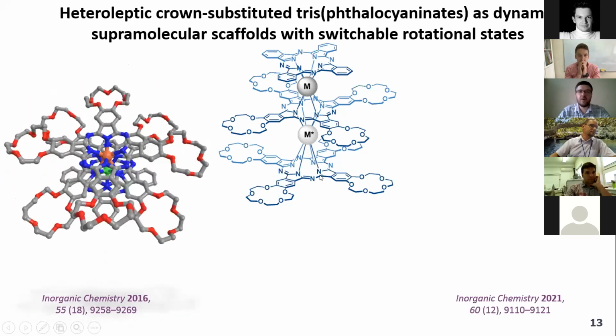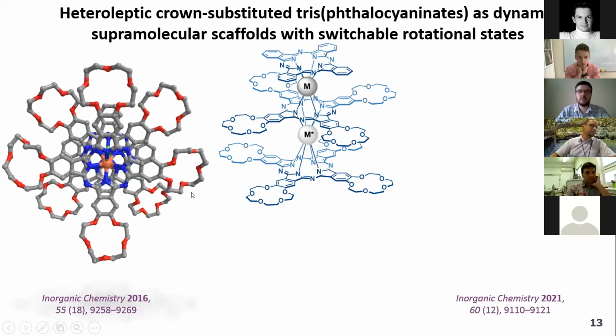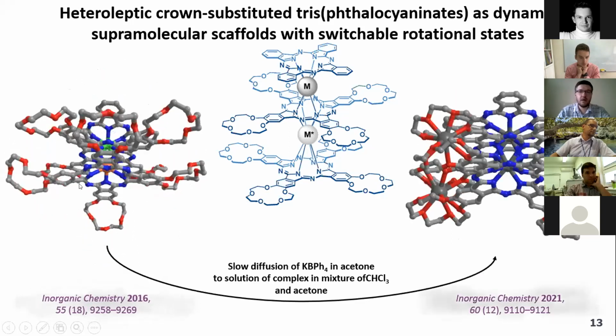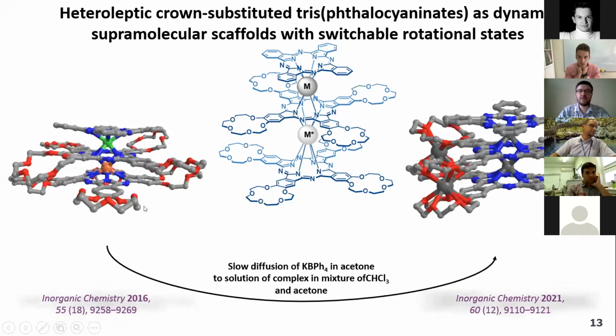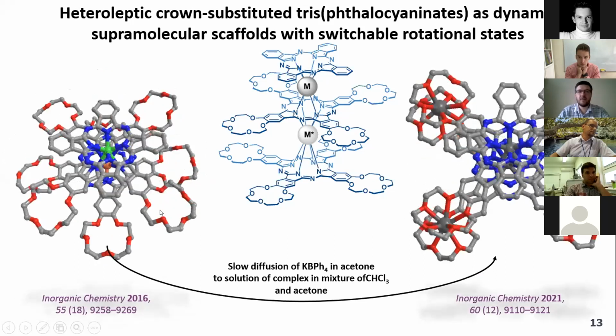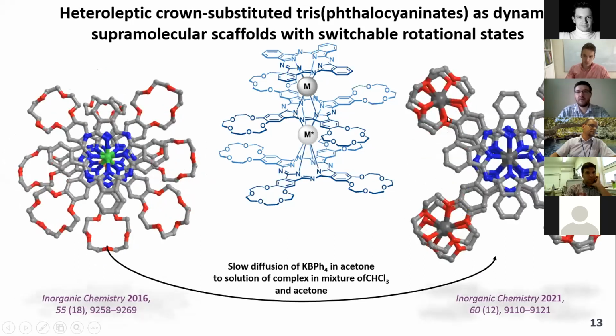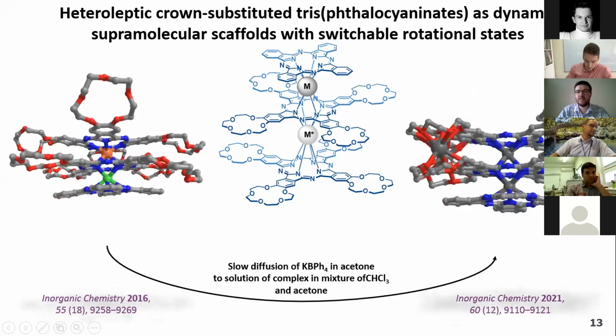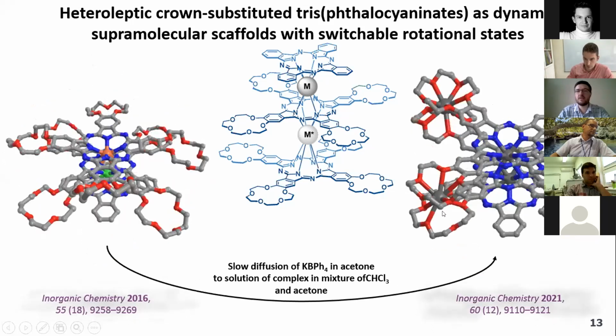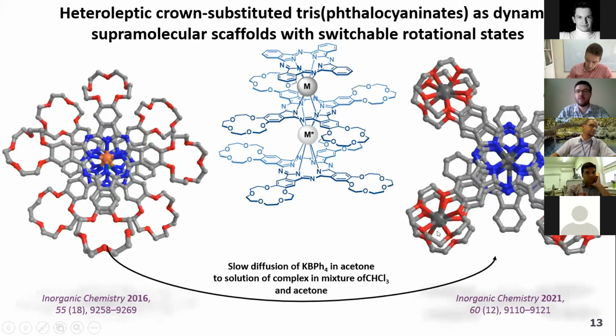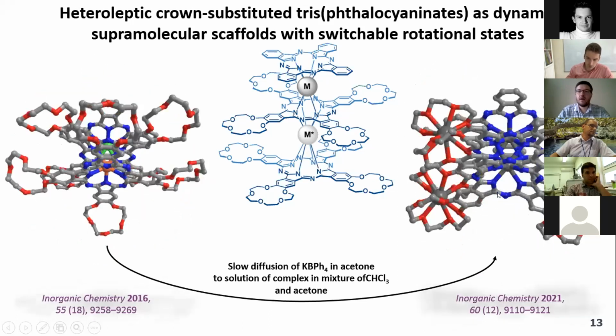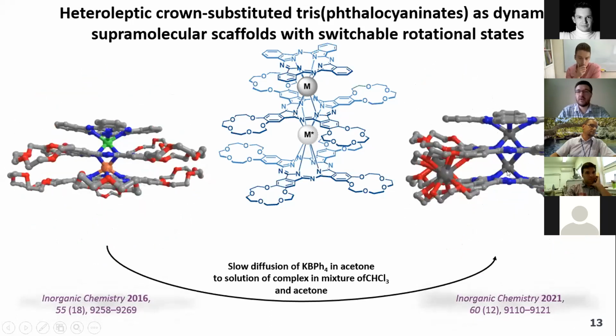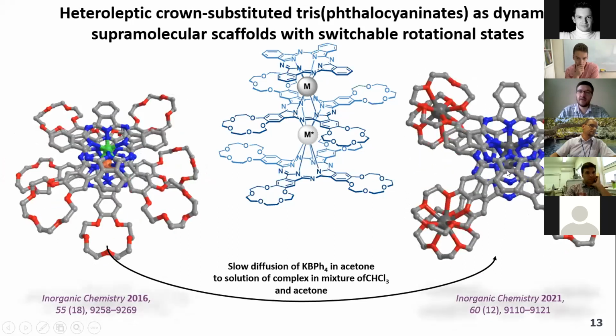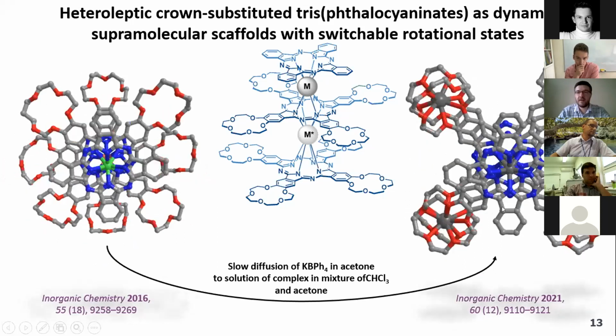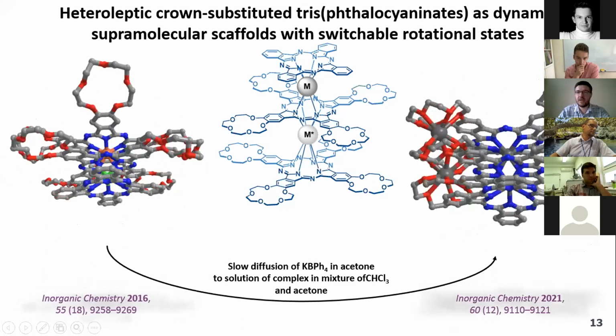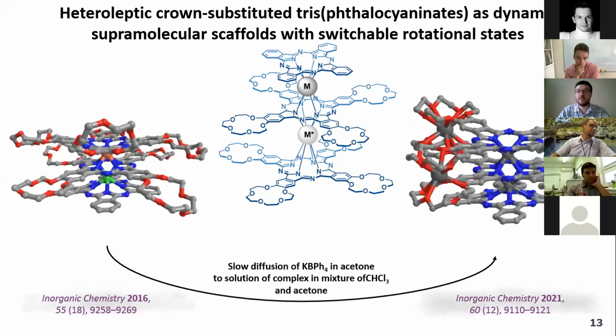But when we add potassium ions, these crown-substituted ligands actually adopt another conformation. They rotate with the formation of an eclipsed state, and potassium ions intercalate between these crown ether groups, changing the coordination polyhedron of this metal ion from square antiprismatic to prismatic. On the other hand, another metal, which doesn't participate in this switching, remains in the square antiprismatic state.